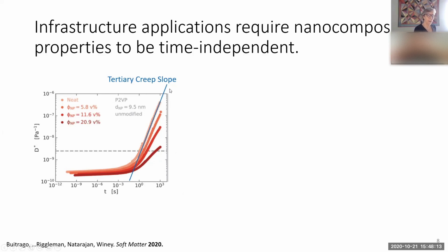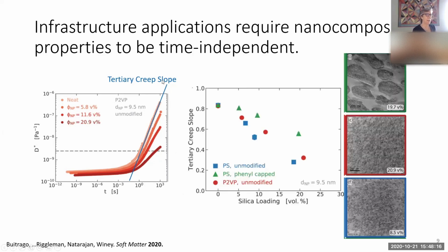And then the other parameter we pull off of this is the tertiary creep slope. So once it starts deforming at long times, how quickly does it deform, right? And so here, these are all silica particles with polystyrene, either with the bare silica particles or phenyl capped. So this is really a weaker interaction in the green data. And then the red data is a strongly favorable interaction between P2VP and silica.